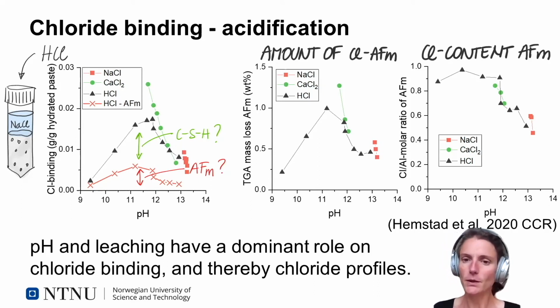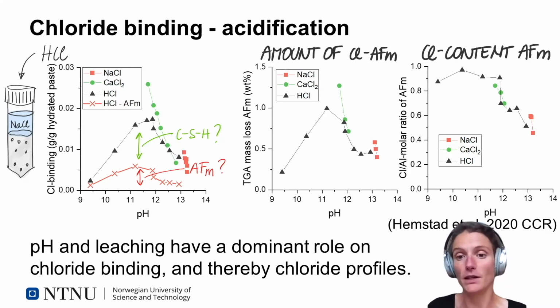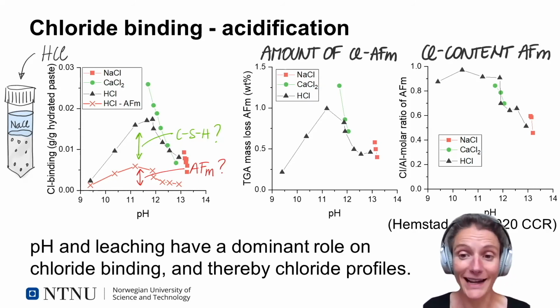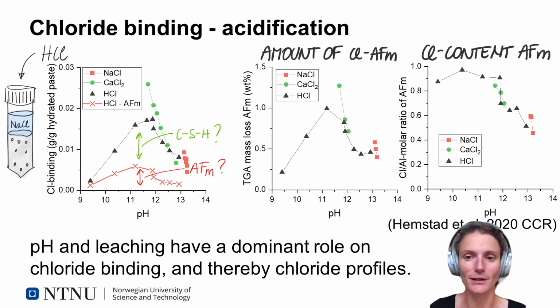When a concrete is exposed to seawater, the outermost section will leach severely. So there we might expect a pH of approximately 9 or 10. And there we see we will have a reduced chloride binding. Whereas slightly deeper into the concrete, we will have a more moderate leaching. So for example, a pH around 12. And in that case, we will have an enhanced chloride binding due to this moderate leaching.